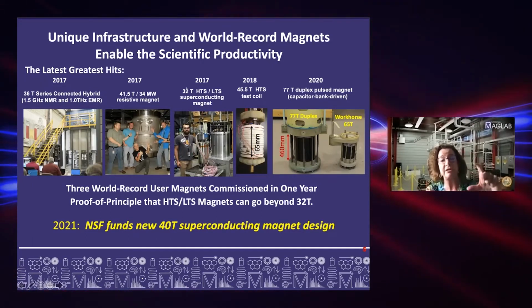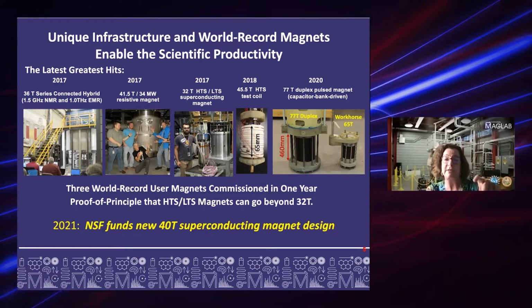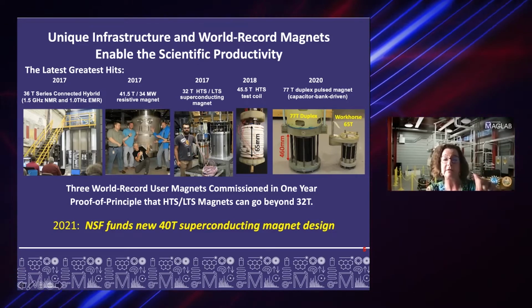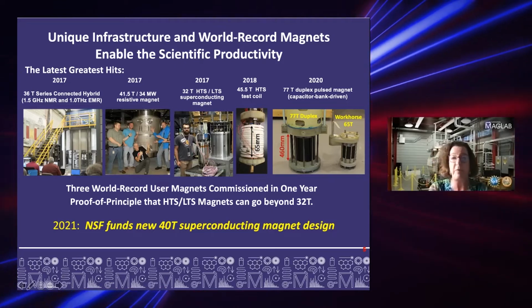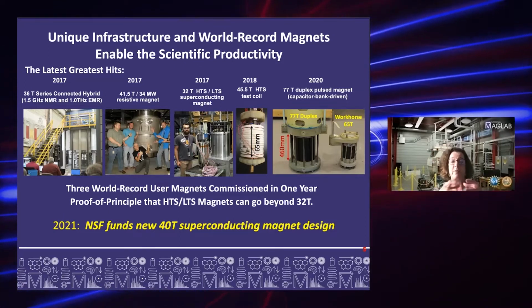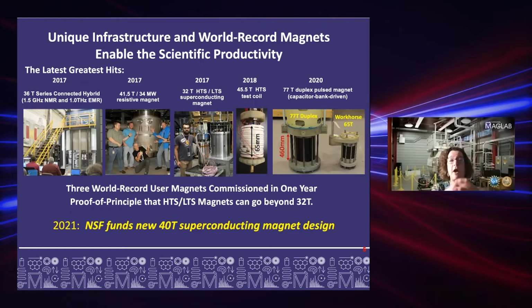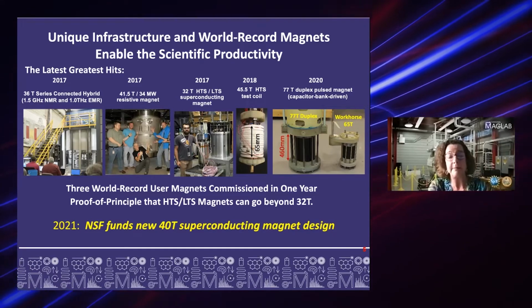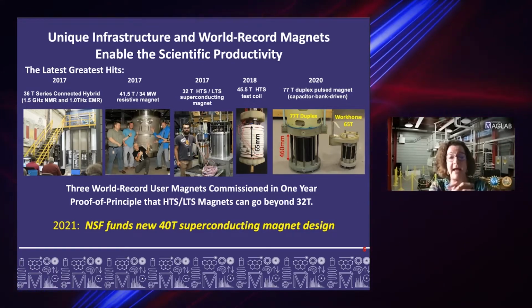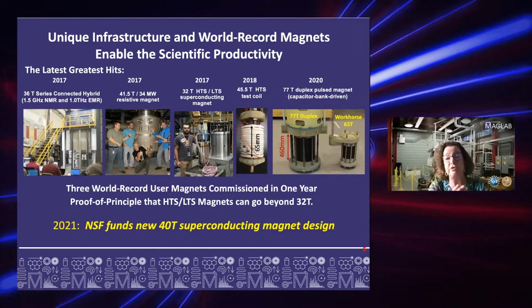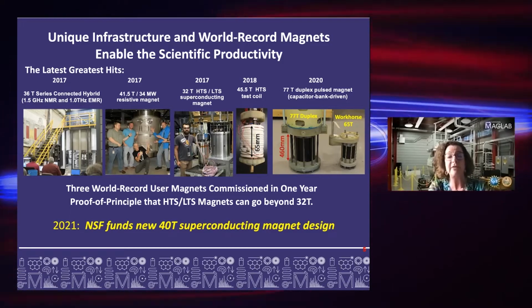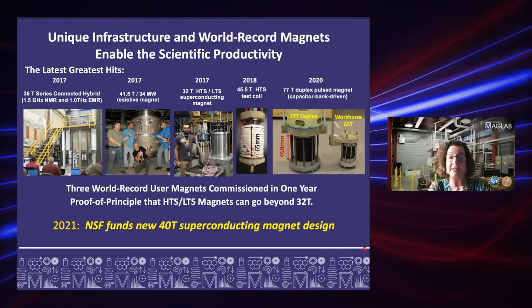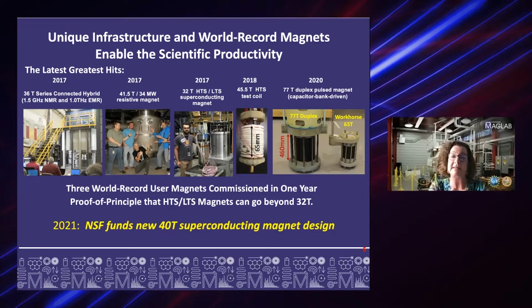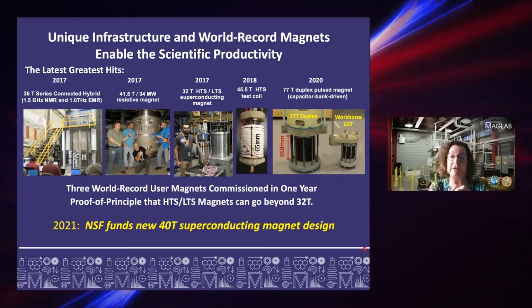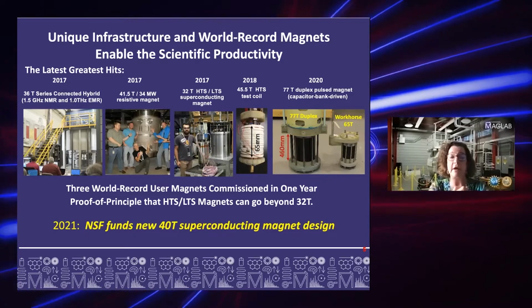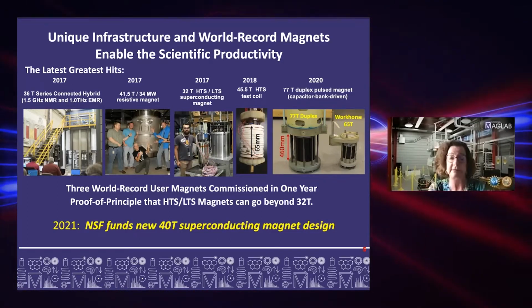We're commissioned to build a 40 Tesla all superconducting magnet. And this one here is a small test coil that went to 45.5 Tesla. It all has to do with what's the insert and what's the outsert. In all of these super high Tesla superconducting magnets, you have to use high temperature superconductors. Both these use REBCO tapes, not because of the critical temperature, but because at low temperature, they're the only superconductors that can take the high fields.